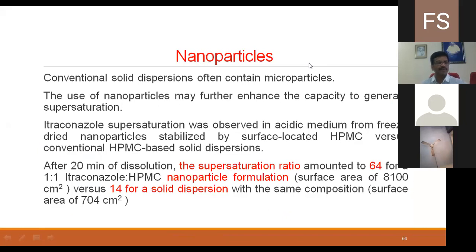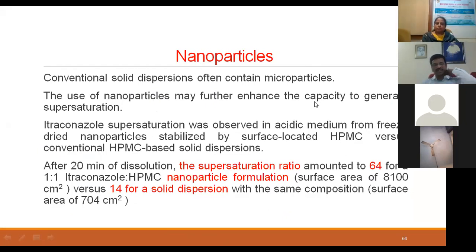Nanoparticles, more focus was given by yesterday's speaker, Dr. Giriraj Kulkarni. Conventional solid dispersions often contain microparticles. The use of nanoparticles may further enhance the capacity to generate supersaturation. Itraconazole was the drug, and itraconazole supersaturation was observed in the acidic medium from freeze-dried nanoparticles stabilized by surface-located HPMC. So the spring effect was obtained with the formulation, and the parachute effect is with the HPMC.